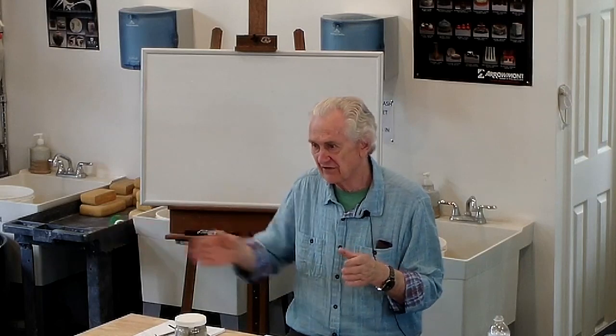And you can do what's called a line blend, where you add a little bit to something and then a little bit more and a little bit more. You could do that with the recipe. Just take a recipe, keep it simple, and follow the recipe. Then add some more and see what happens to the glaze as you increase or decrease the amount of the material. That way you can cover a range and see whether it works. Do you find an area that works for your range?